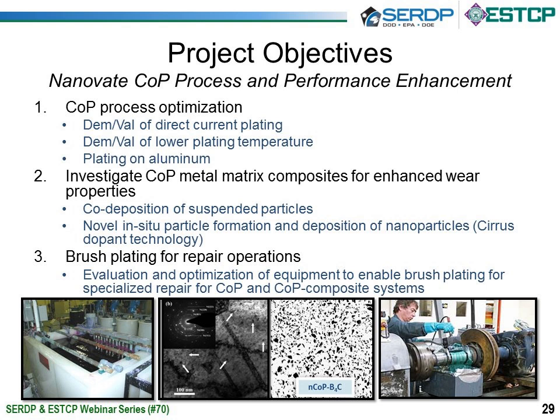The project objectives we divided into three main areas, looking at the material for use in repair operations, but also at ways we can improve the process and performance. The first objective involves optimizing the current cobalt phosphorus process, with modifications to the chemistry so that we can do direct plating. We're also looking at ways to lower the plating temperature of the solution to make it more compatible with existing processes at Fleet Readiness Center. And since we're also looking at potentially repairing aluminum structures, we want to see if there are any tweaks to make it more suitable for coating aluminum substrates.